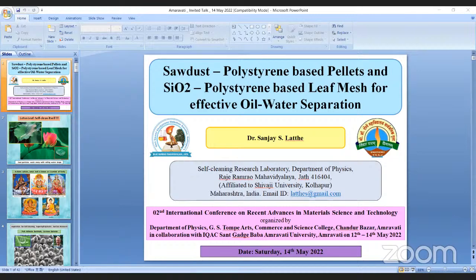Next. We have calculated the oil water separation efficiency of these sawdust pellets and how many times we can use these pellets for oil water separation. We observed that around 98% of the hexane was separated. Kerosene is also 98%. Diesel also 98%. Coconut oil is around 95%. Maybe it is because of the viscosity of the oils. Highly viscous coconut oil may get trapped inside the sawdust pellets, and that's why the separation efficiency is lower.